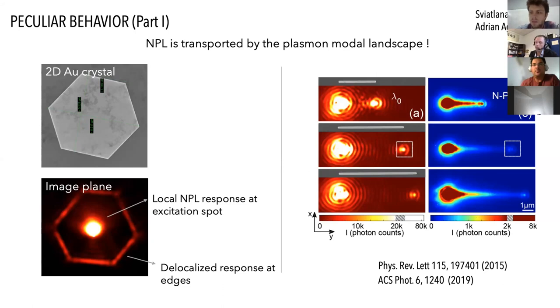But if it is a heat source, my vision is the following: of course it's a heat source, but the heat source for the electrons, right? So you get the plasmon, which sucks up your input energy, and the plasmon is propagating down the structure, and of course the plasmon has some losses. These losses will basically heat up the electron gas because it's a pumped plasmon, a 200 femtosecond pumped plasmon. During the propagation, it will exchange its energy with the electrons as any kind of optical excitation. Everywhere inside the structure where the plasmon goes, it excites electrons at a temperature which is proportional to its local electric field.